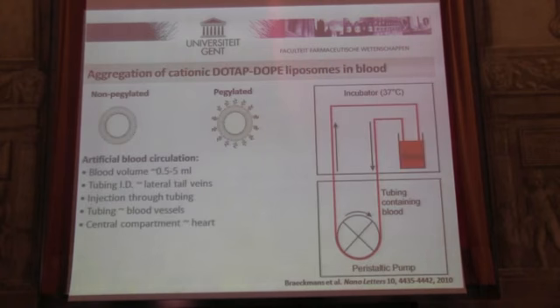So we use this system now to study, for example, the aggregation of cationic liposomes that are being used for nucleic acid delivery. We compared non-pegylated ones, pegylated ones, and we started off with this very simple artificial blood circulation system. It makes use of plastic tubing with a diameter that is comparable to the lateral tail vein of a rat. We took human blood in this case, so we have many students that had to donate a little bit, you know how it goes. So this is student blood. What we do is we have a vessel with this blood, and then we have tubing going out, coming in, a very simple pumping system. Everything is put at 37 degrees, and this is our artificial system.